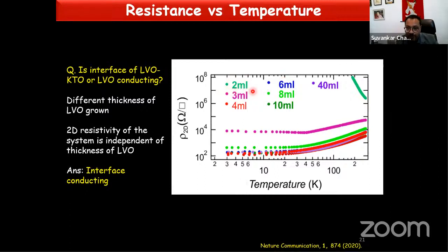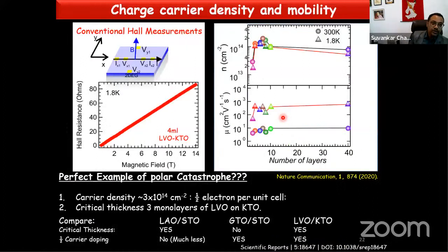So this is the resistivity data of different monolayer samples. ML corresponds to monolayer. This is temperature versus resistance. For the 2 monolayer sample, it's completely resistive, but after 3 monolayers, the resistivity decreases with decreasing temperature, and it becomes independent of the number of monolayers of the thin film you are growing. So this is the conventional Hall measurement, which suggests that the charge carrier density is around 3 times 10 to the power 14 per square centimeter in the system, which is actually equal to half an electron